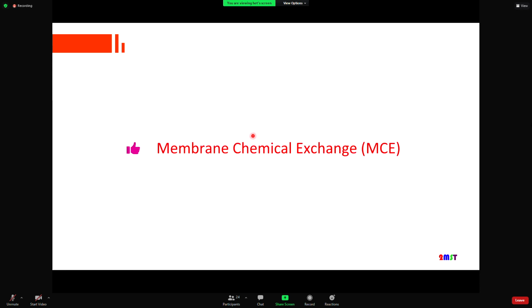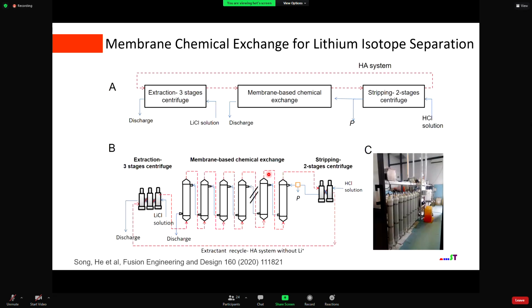Now, I will introduce how to use the EVAL membrane for lithium isotope separation by membrane chemical exchange. Again, membrane chemical exchange for lithium isotope separation consists of 3 steps: extraction, chemical exchange, and stripping. This is a photo of the system we built in our lab to enrich lithium isotopes, especially lithium-7. We use centrifuges to do the extraction and also the stripping.